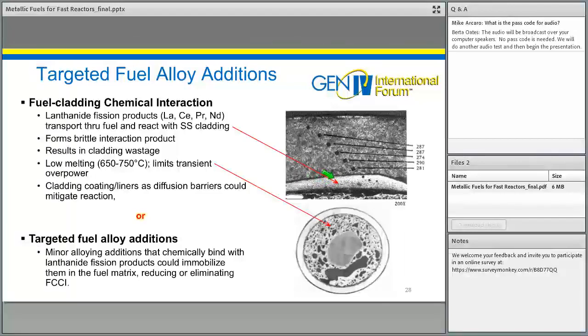And so it doesn't tend to be a problem under normal operating conditions, but under any sort of transient overpower condition, what you can get is melting at that reaction product, which will then propagate into the fuel. So this is a limiting performance feature of metallic fuel. One way we're attempting to address it is by developing cladding, coatings, and liners to act as a diffusion barrier.